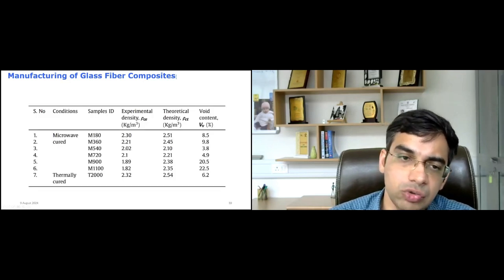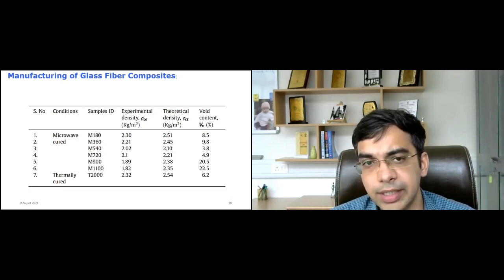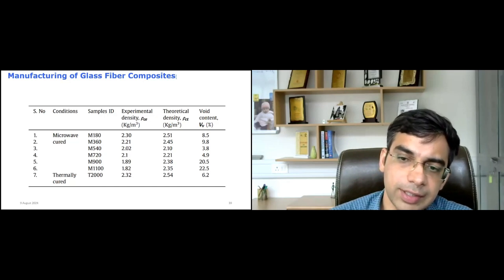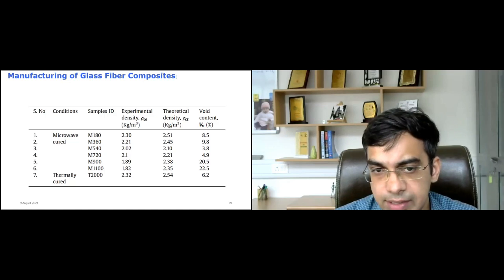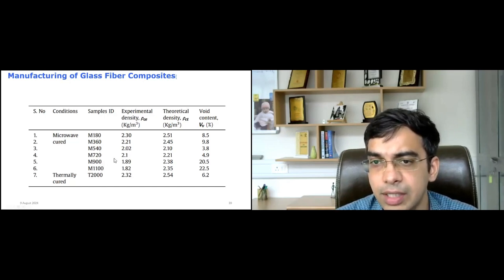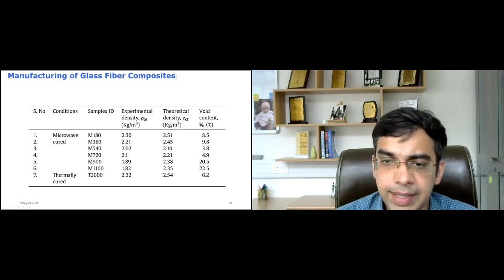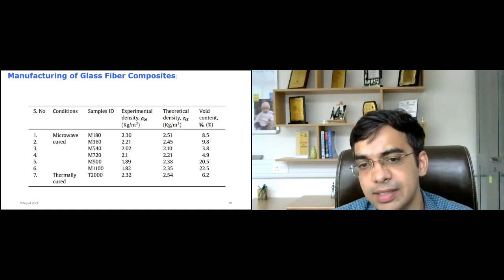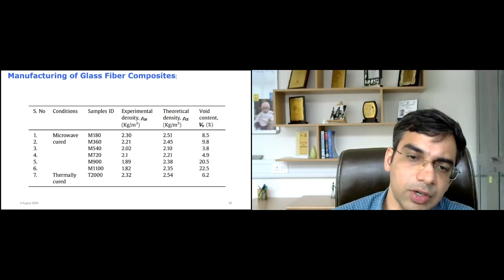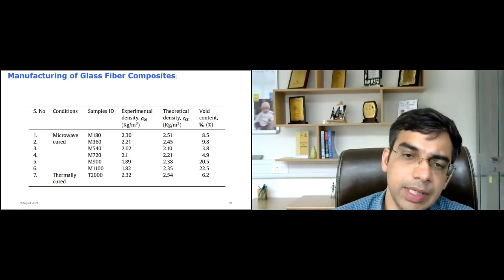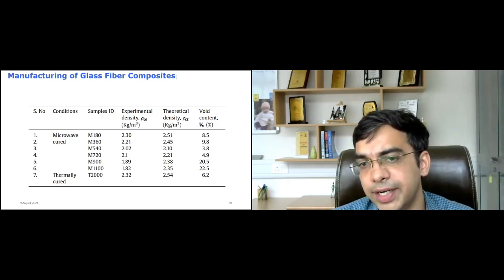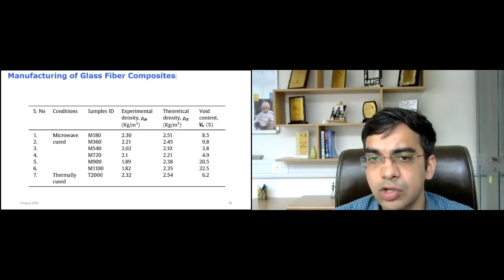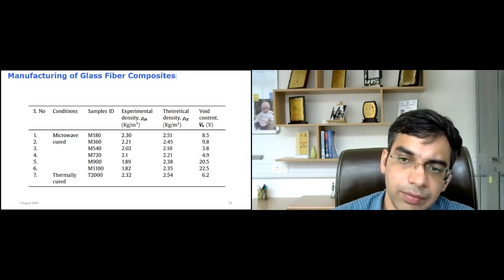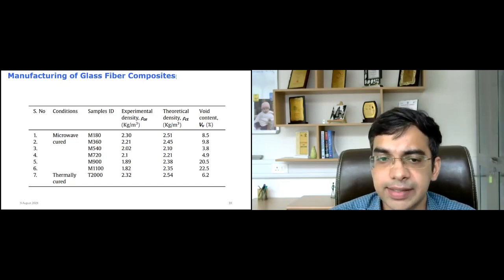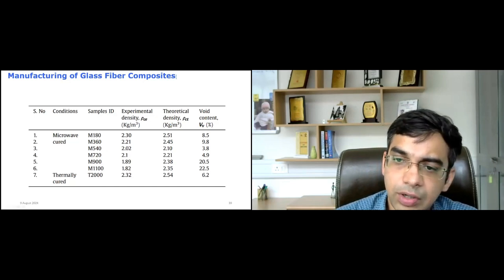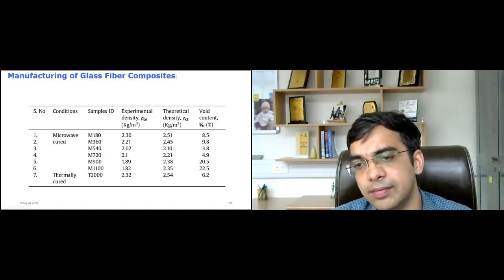So based on this, we also did some characterization of the composites which were developed in terms of the density, theoretical density and void volume fraction. So what we observed is that at different microwave powers, that is 180, 360, 540, 720, 900 and 1100 watt, the density was almost comparable to the theoretical density. Of course, every time the experimental density in any process is less than the theoretical density, because no manufacturing process is perfect, and there may be some incidences of voids or discontinuities inside the composite, which results in a lower experimental density compared to the theoretical density. The void volume fraction was also calculated using this data, and at optimized microwave exposure, say at 540 watt, a void volume fraction of almost 3%, or less than 5%, was observed.